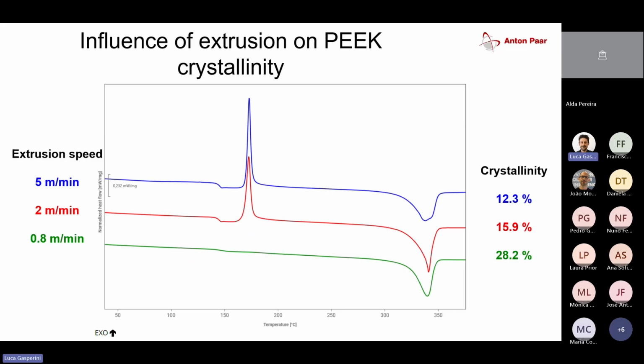And we can also use the integration of the cold crystallization and of the melting to calculate the initial crystallinity of the material. So you see 12.3, 15.9 with the products that didn't really crystallize fully during the cooling, and more than 28% crystallinity of the product that was actually drawn slowly, 0.8 meters per minute.